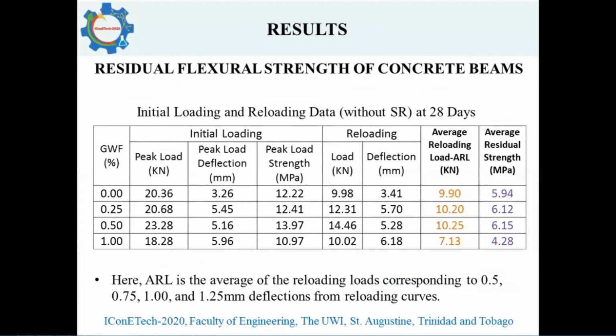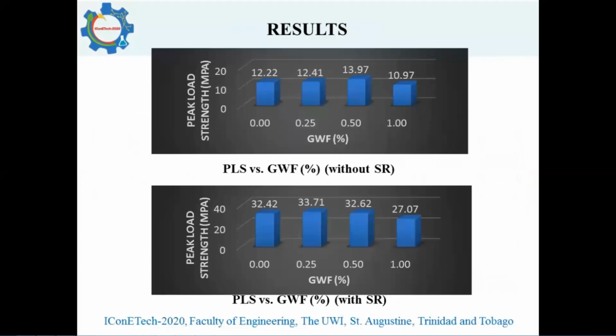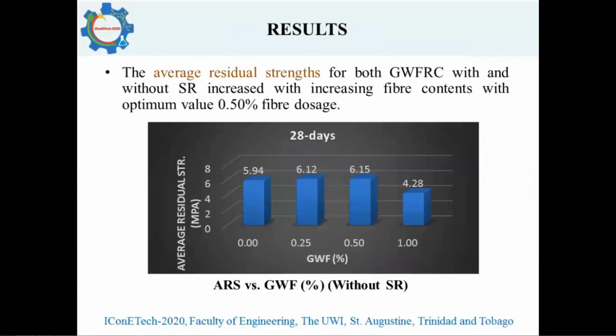Evidently, the average residual strength for both glass wool fiber reinforced concrete without and with steel reinforcement increased with increasing fiber content with optimal value at 0.5% fiber dosage. And then these are the bar charts for the results.